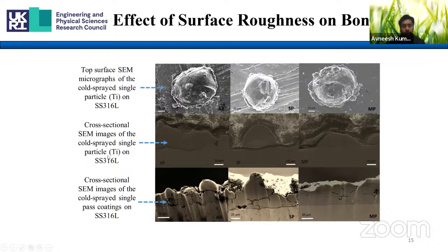cold sprayed titanium particle. There we have seen that in the case of semi-polished, there was no bonding. However, in the case of as received substrate surface, there was good bonding and the particle was able to deform. But in the mirror polished substrate surface, the particle was able to deform completely and it adhered very well with the substrate.